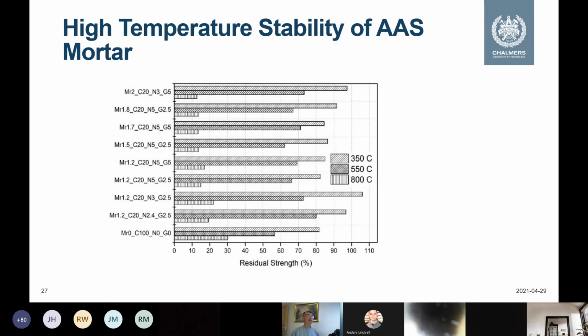So the reason is that after 800, in fact, everything in the cement materials has been destroyed. CSH has been destroyed. But at 550, it is only the Portlandite in Portland cement that is destroyed. For alkali-activated concrete, we have less Portlandite. So this is why alkali-activated concrete has better stability to high temperature, up to 550. If it is higher than say 800, it is not good enough.